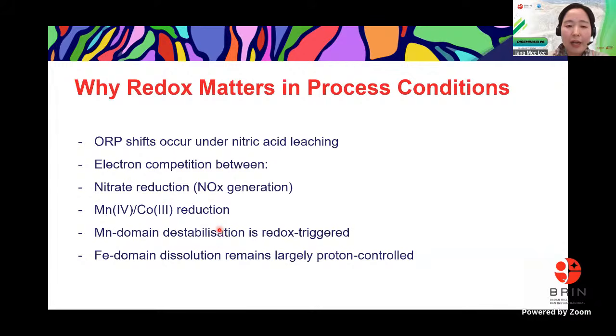But in contrast, the iron oxyhydroxide, like I mentioned in the previous slide, the goethite dissolution remains largely governed by the proton-promoted mechanisms under the same nitric acid condition. So therefore, the redox perturbation does not merely accelerate the dissolution kinetics, it modifies the sequence in which the mineral domains destabilize and dissolve. So from the processing perspective, this distinction is really important, I personally think.